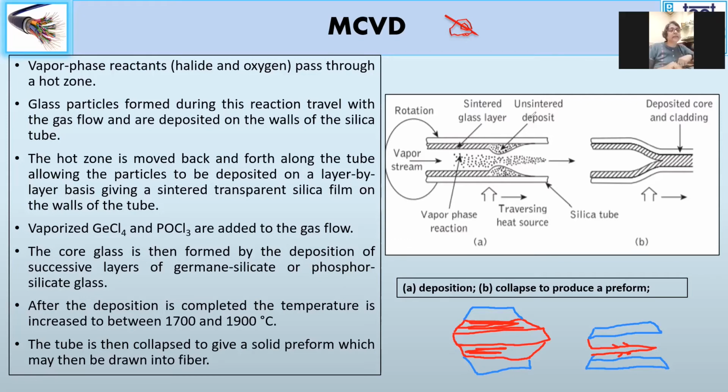1900 degrees centigrade. And what happens is, the outside silica glass that you see collapses, and what you get is the pure preform, which does not have any kind of cracks, because you tried to pull out the starting material on which this preform was getting deposited, and therefore you get the solid preform. At high temperature, the outside glass will simply get broken out, and what remains is a solid preform.